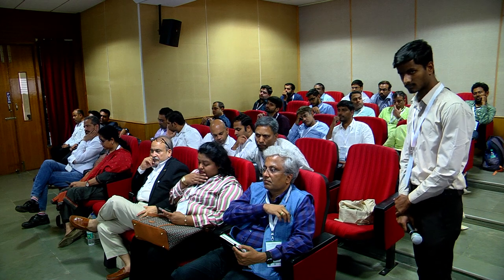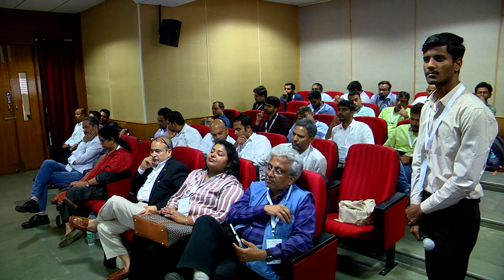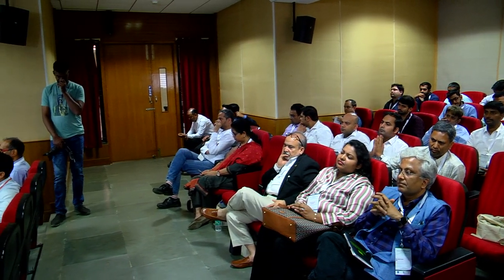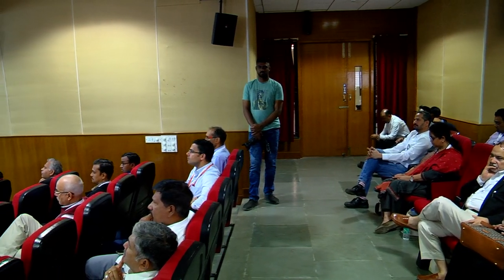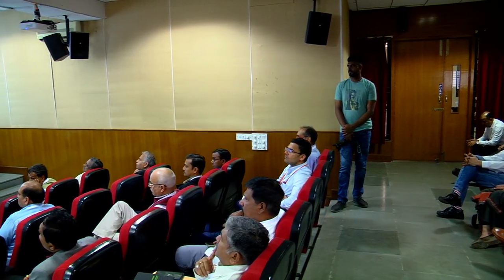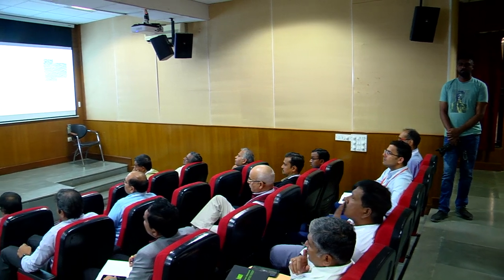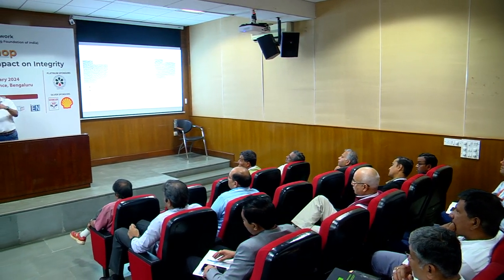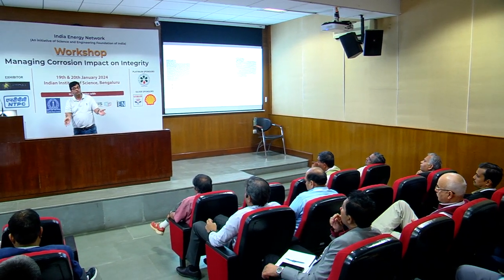Yes, so we have done some work on high entropy alloy coating, which has several kinds of components, and to which we have added carbon nanotube. What we interestingly observe is that whenever you have carbon nanotubes present in the coating and near the surface, the oxides which are formed of the metal are more stable than the other oxides. You have different oxides of the same metals. The more stable oxides are always present in the coatings which have carbon nanotube near the surface.